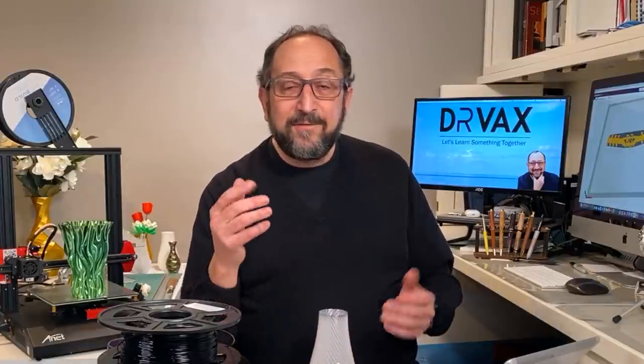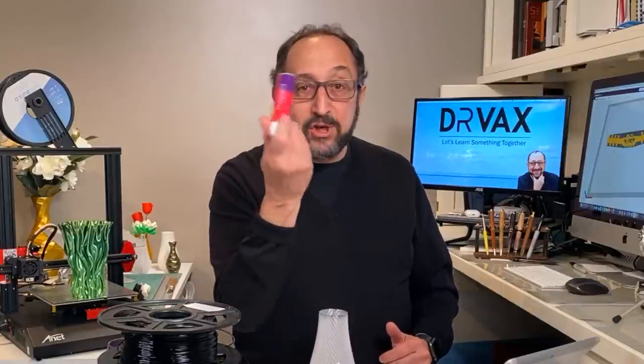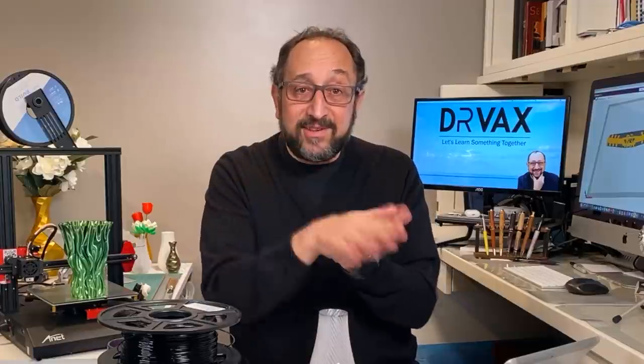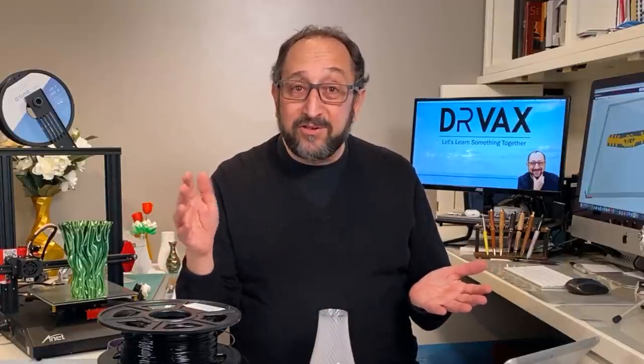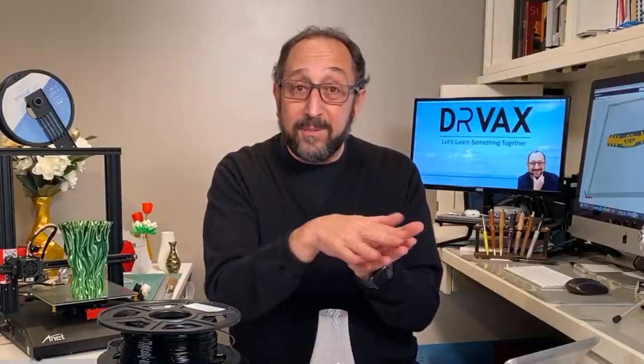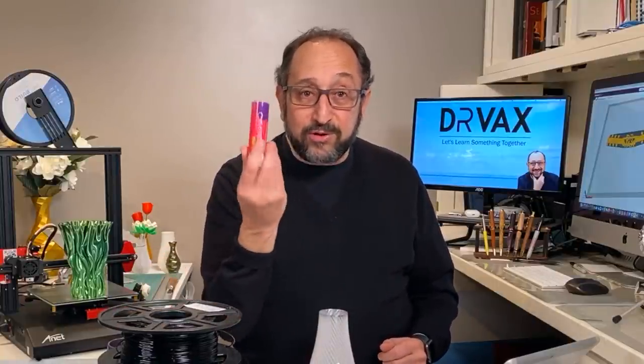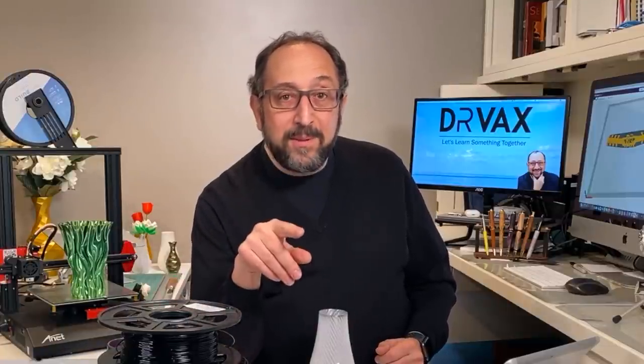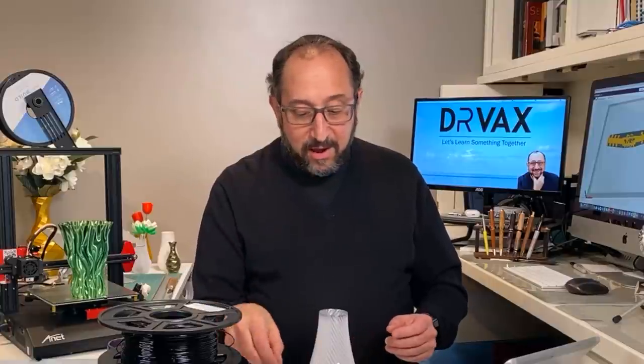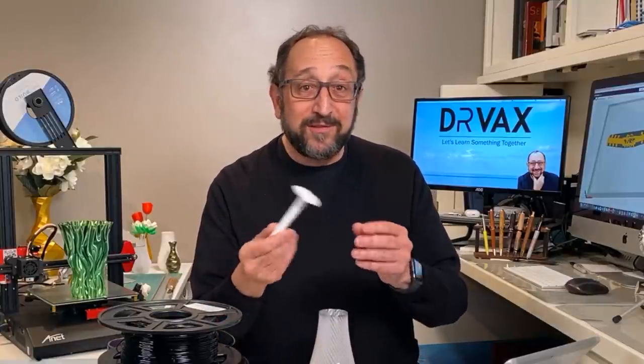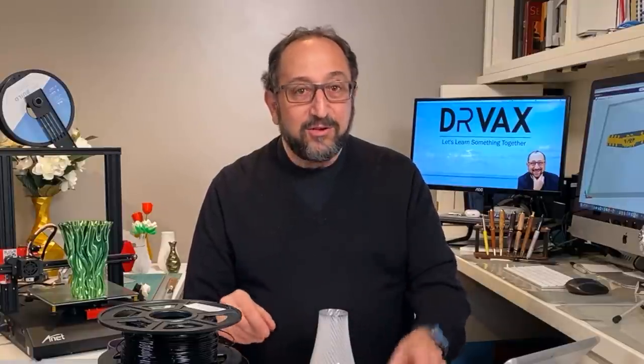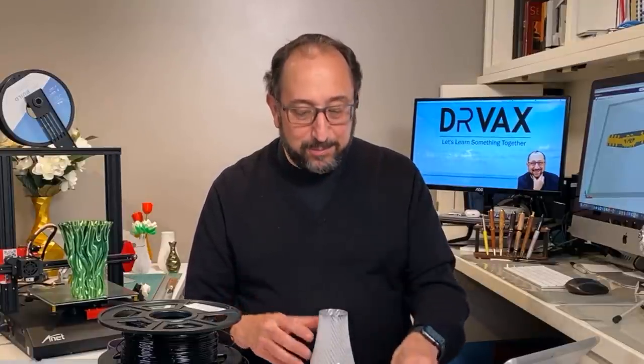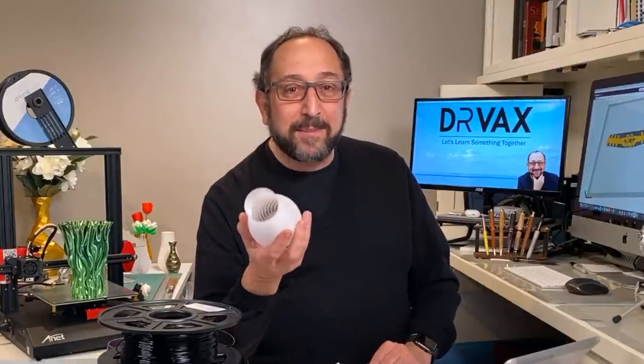So in summary, if you level your bed, you get the temperature right, maybe you tune retraction a little bit, and most importantly, you use a bed adhesion material so you both can stick to the bed and release from the bed, because PETG does stick layer to layer very well. So some materials won't release well unless you use something on there. You have the ability to print PETG on printers ranging from $200, $250 Anet ET4 printers to $500 Monoprice Ultimate 2 printers to $1,000 Prusa i3 MK3S.